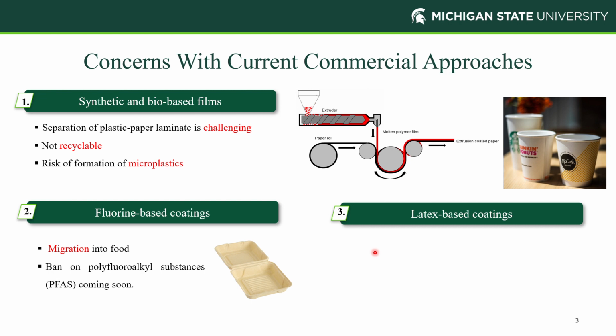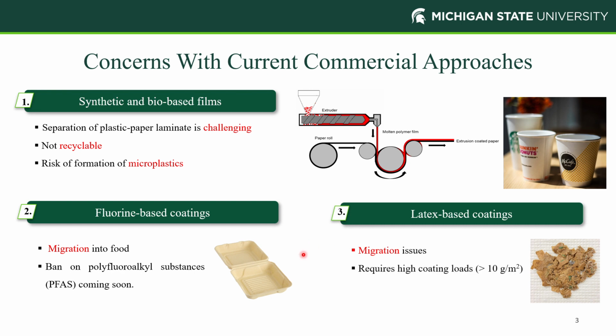And talking about the latex-based coatings, they also face some migration issues, and they also require higher coating loads on the paper in order to produce good properties. And the major disadvantage of latex-based coatings is that they form stickies during the recycling process, which hinders the recyclability of these papers coated with latex-based coatings.